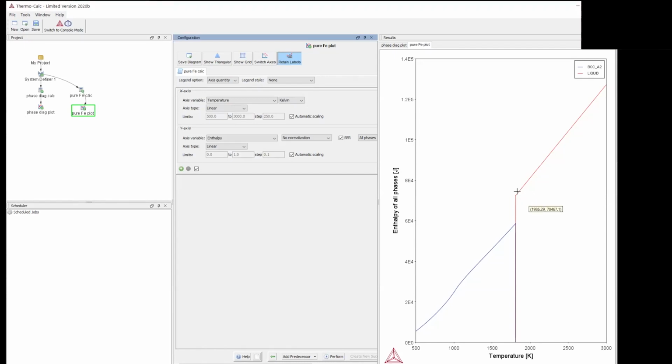Yeah, so I'm just going to mouse over, right? Your boss is hovering over you. You need an answer quickly. Here we go. You see? Can you guys see how I mouse over? It's giving me the value at the cursor. So I'm going to say 72,416 minus 58,445. That's it. That's my estimate of the transformation enthalpy. And I'll say maybe that's good to 2 digits. So I'm not going to carry 5 digits of significant figures. I'll carry 2 digits. So if someone asks you for the transformation enthalpy from this plot and you were in a hurry, you just mouse over or take a ruler or any other method and estimate the value.